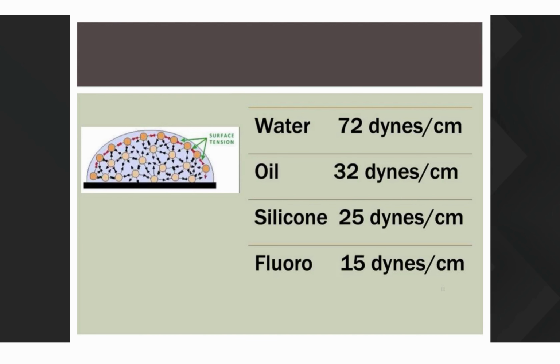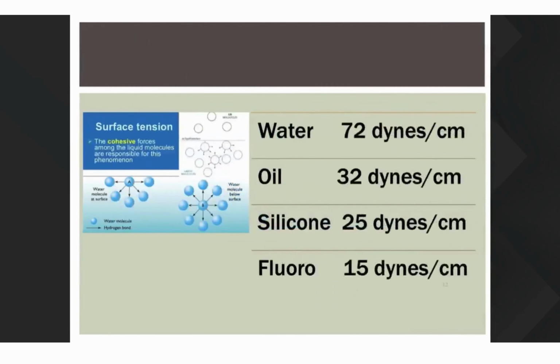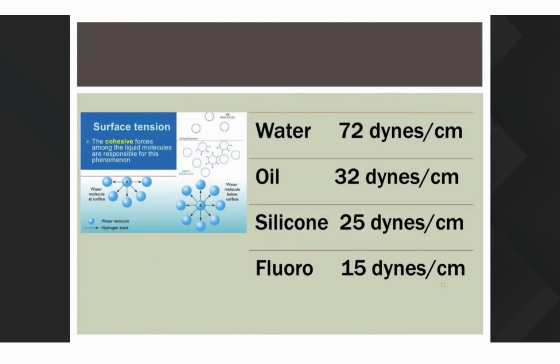And this gives a great opportunity by using these systems to assemble these self-assembling units so that at the surface of the formula, you can feel the lower surface tension. When you get the lower surface tension, you get spreadability, you get rheology, you get foam. But if you don't lower surface tension, you don't get any of these. And that's a critical thing, and it doesn't need to be a big change. So many other polymers can do this as well. When we put fluoro compounds in here, now we're down to 15.